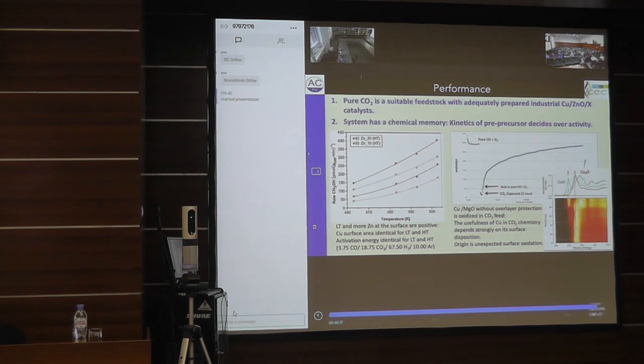And if you are one of the old literature readers in this area, then you might remember an important researcher in this area was Kamil Klier from America, and he published all of his life publications where he said the active state of the catalyst is copper 1. And nobody believed it, because when you do X-ray diffraction, you find it's a copper metal. And it is bulk copper metal, but the surface is oxidized, at least partly. It's a mixture between copper 1 oxide and copper metal that is active. And if you have too much CO2 and no zinc oxide on the surface, it all converts even into copper(II) oxide. So CO is the poison that you get here.